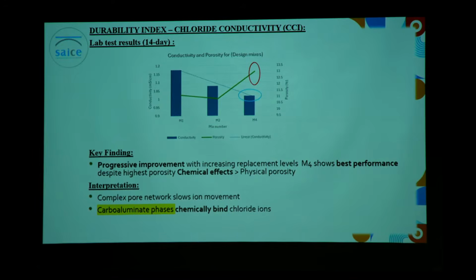Now, this was kind of confusing because with the other tests, the sorptivity, also the OPI, we were having poor results, but the chloride conductivity was generating much better results. This was due to the fact that the physical structure, the pore structure, is still in a development stage. However, if we look at the chemical microstructure, we're already witnessing our chemical benefits due to introducing our limestone calcined clay.